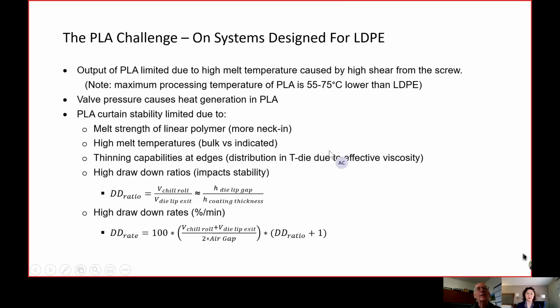We also are fooled sometimes. We're going to talk a little bit about, I'll say, the average temperature versus the indicated temperature of the polymer. And sometimes we can be fooled, again, because of the equipment that we're running on and not recognize the over temperature that we're putting into the PLA on conventional extrusion coating equipment. The viscosity of the PLA at these lower temperatures may also reduce the distribution to the ends of the die, which will also affect the stability at the edges.